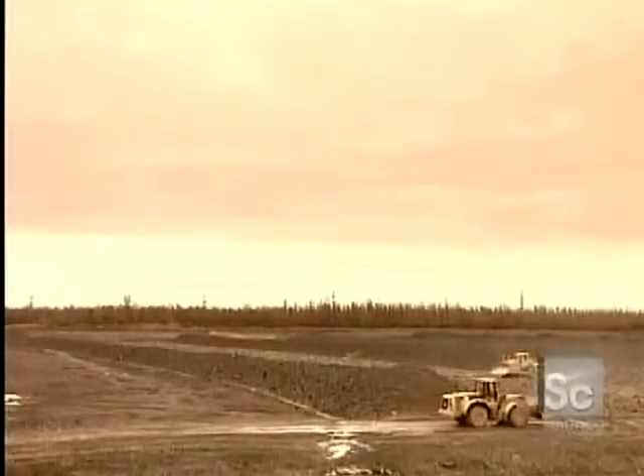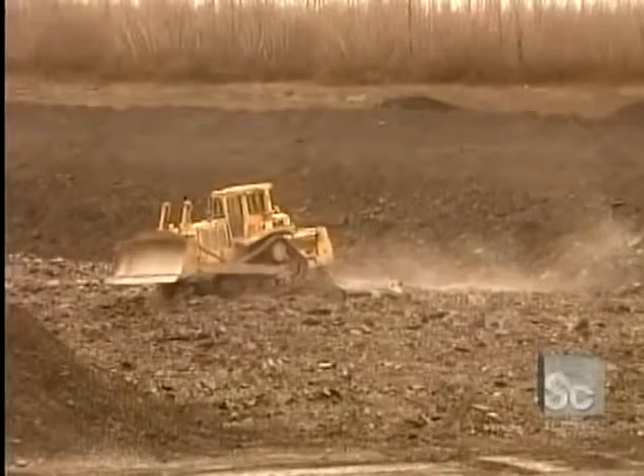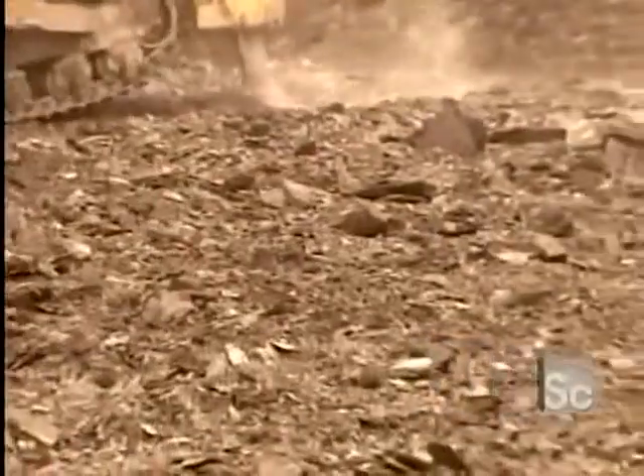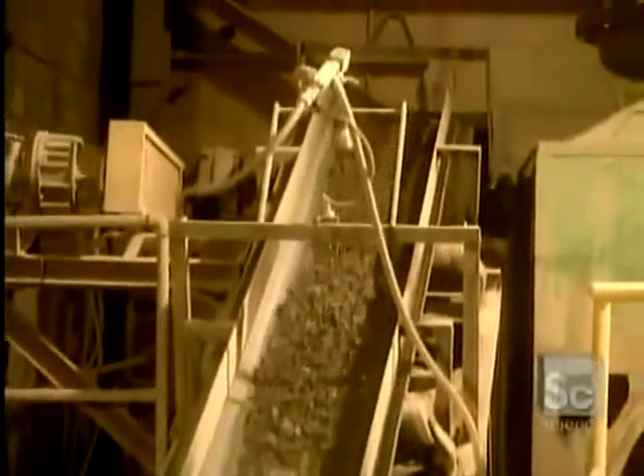Bricks are often made of shale, a lightweight rock that splits easily into thin layers. Quarry machines dig 16 inches down to expose the shale to the elements for 2 years. This weakens it, making it easier to process once it gets to the factory.